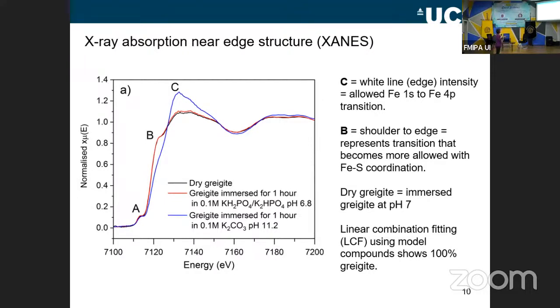B is a very special feature that we only see for iron sulfide materials, because it's a transition that's not allowed usually for iron, but the bonding with sulfur, because sulfur is very soft, means that you get some mixing of orbitals, which means you get some transitions which aren't usually allowed, which are allowed.